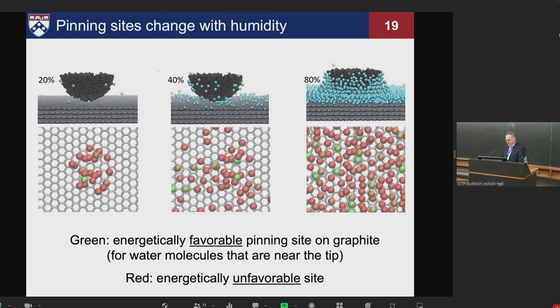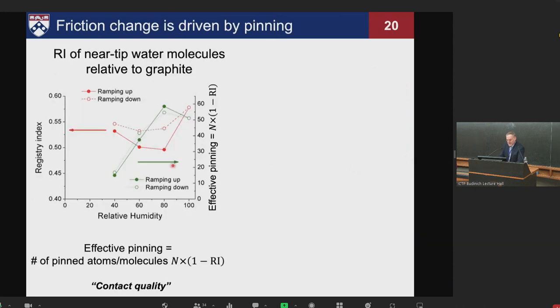that there are more adsorbates total, and you see that there are more green atoms, ones that are more favorable in terms of being pinned, being low energy, and thus more difficult to take out of that site. And then as we go to very high humidities, you can see what looks like a capillary, and many more of these atoms are indeed in energetically favorable sites. So what we can do is come up with what we call an effective pinning parameter.